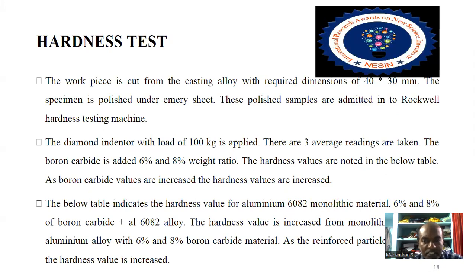Next one is hardness test. The workpiece is cut from the casting alloy with dimensions of 40 by 30. The specimen is polished with emery sheet. The polished samples are placed into a Rockwell hardness testing machine. A diamond indenter with a load of 100 kg is applied. Three readings are taken and averaged. Boron carbide is added at 6% and 8% weight ratio. The hardness values are noted in the below table.